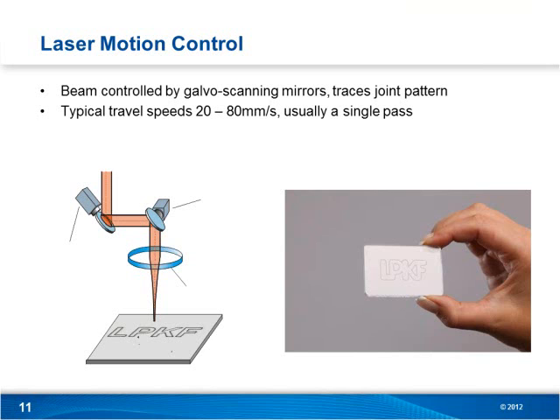So typical travel speeds, we're seeing 20 to 80 millimeters per second as working travel speeds, but different than through transmission laser welding, where a lot of times we're making multiple passes. Here we're usually making a single pass, maybe 2, 3 at the most. Tony, you might have different experience with this, but for the most part a single pass can usually handle what we're looking for. So even though the travel speed might be slightly slower than regular through transmission laser welding, because we're only making 1 or 2 passes, it's still a very fast process and absolutely adequate for production.